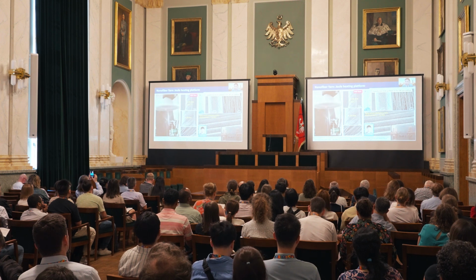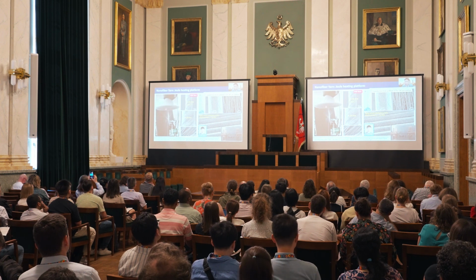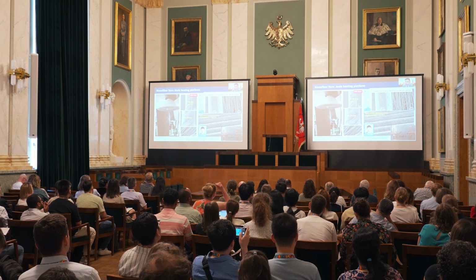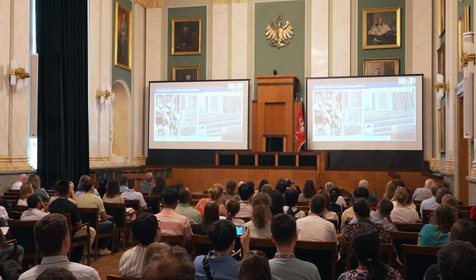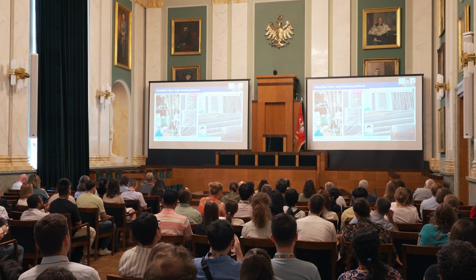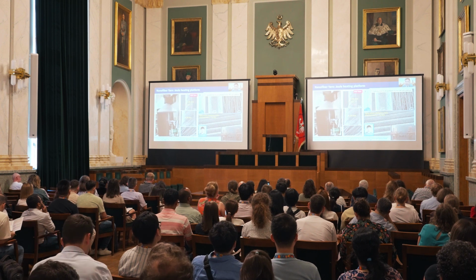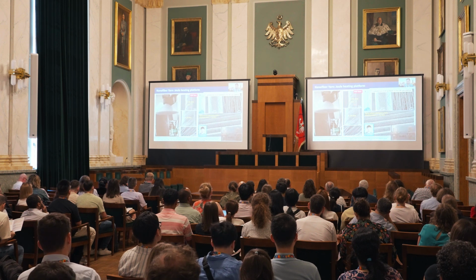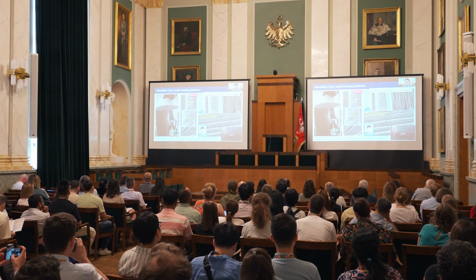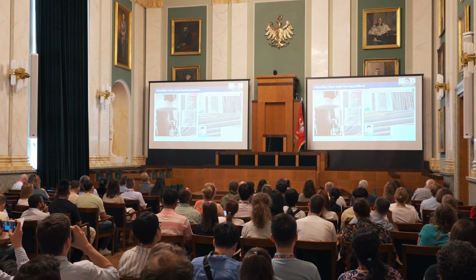As a case study, we use the nanofiber yarn technique. At the last Malaysia electrospinning conference, my colleague and friend, Professor Andreas Reiner, introduced this yarn spinning technique. We also use this technique for the nanofiber synthesis. So this is a 260 micrometer thickness. Then individual fibers are entangled, so we expect a high surface area. After the carbonization process, we could synthesize carbon nanofiber yarn.